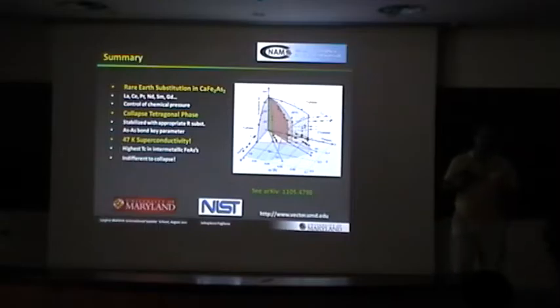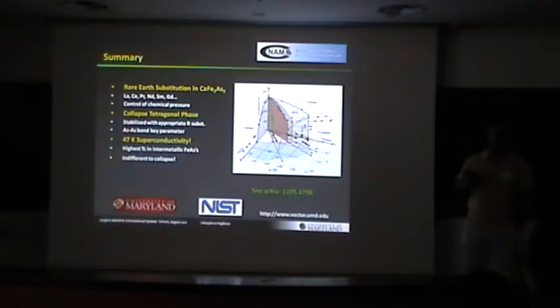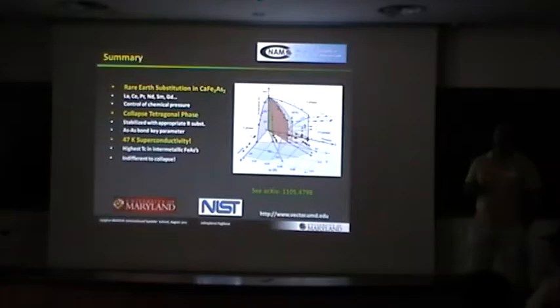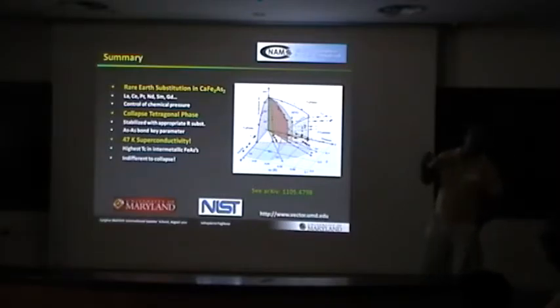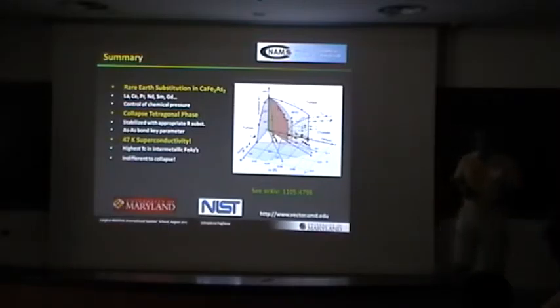Where I said the strain-induced superconductivity, I believe, is somewhat different. First of all, the strain-induced superconductivity in calcium-122 is maximum 10 Kelvin. Never seen above that temperature. Right. There's some evidence for that in the other 122 materials, up to 20 Kelvin. The superconductivity we see here is approaching 50 Kelvin, and I believe it's of a different nature. Now, how do you have one and not the other? I'm not sure, but I can say in some samples.